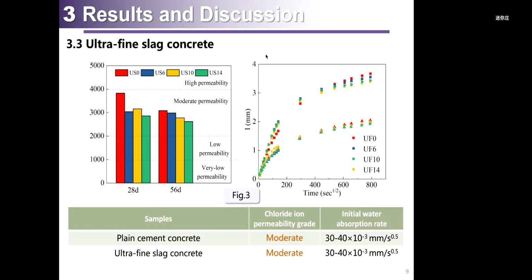And there is almost no difference in the initial water absorption of the concrete with various ultrafine slag content. It reflects that although the ultrafine slag has a much larger specific surface area and thus higher activity than ordinary slag, it cannot further effectively refine the pore structure compared with the ordinary slag, especially with small content.